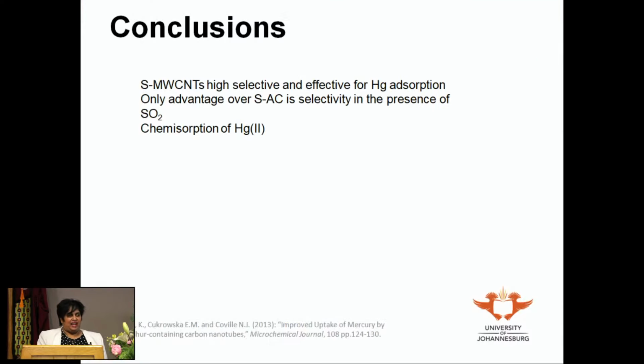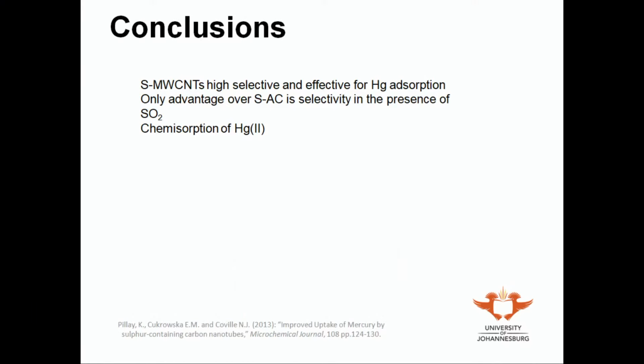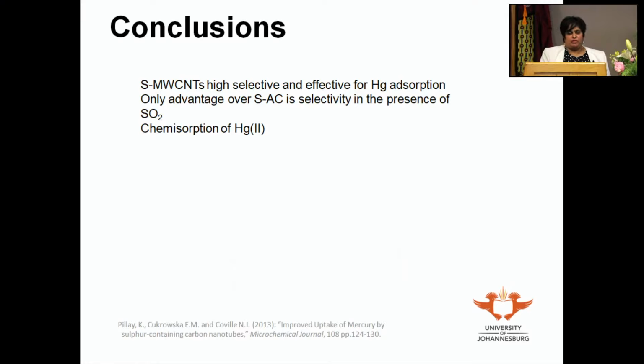Some of the highlights of the study were that we found that sulfur-containing multi-walled carbon nanotubes were very effective for the remediation of mercury-2. There was not that much of a difference with the performance of sulfur-containing activated carbon, but we found that it was highly selective in the presence of SO2, and that's where the sulfur-containing multi-walled carbon nanotubes outperformed the sulfur-containing activated carbon, and there was a definite chemisorption of mercury-2. This was work that we published in Microchemical Journal.